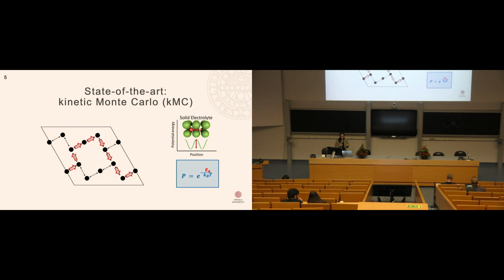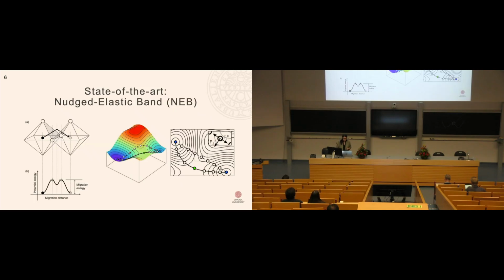So to compute the probabilities of each possible transition, we need information about all the different energy barriers of transitioning from one energy minima to another. And this is, of course, where the big challenge comes in. How do we get these energy barriers? So the most common approach is to compute energy barriers by identifying the minimum energy pathway using, for example, the nudged elastic band method.